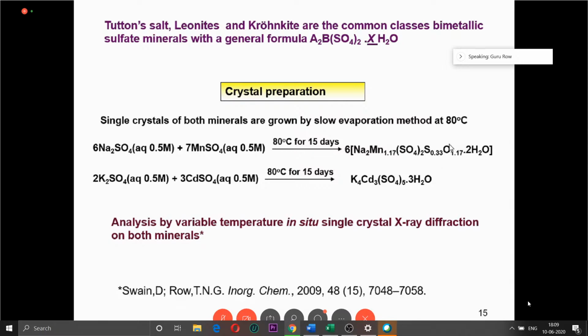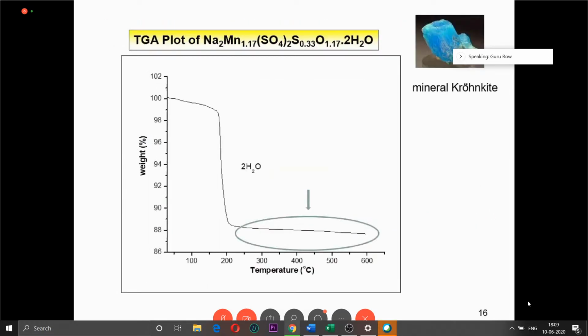You see that it is a non-stoichiometric ratio of elements, and this is very interesting because it is the non-stoichiometry of these elements along with the presence of water which will allow for the possibility of the generation of new phases. This we realized as we went along in our research over the last 10 years, as you see that this reference goes back to 2009. So analysis of variable temperature in situ single crystal diffraction of both these minerals were carried out, and because of lack of time, I'll cover only one of them in full detail.